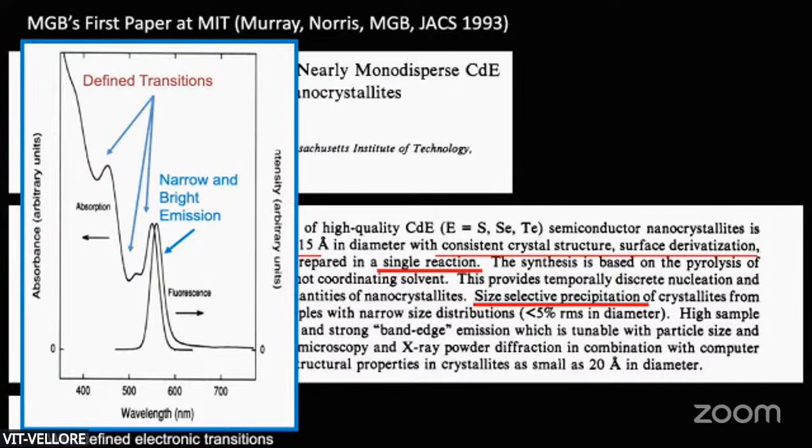The paper also talks about characterization, because it turns out that when you have a new nanomaterial, you need to characterize it in so many ways. So we talked about using electron microscopy, X-ray diffraction, all the tools that today are the standard tools when you have a new nanomaterial that you characterize to really understand it. And one of the tools, because these are optical materials, was just to do simple absorption and emission properties. And you can see here in this spectrum, in absorption, now we see multiple peaks. What are these peaks? Well, the peak that is the closest in the reddest is the fundamental, right?